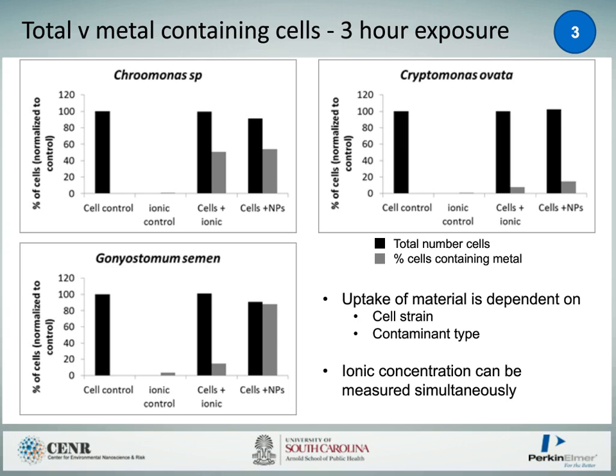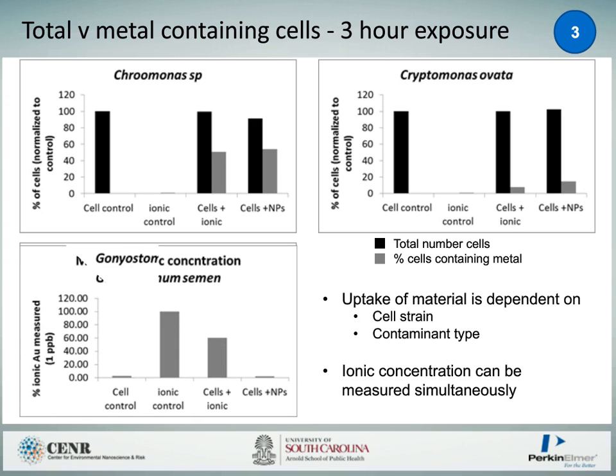You can also measure the ionic concentration simultaneously. So here I just wanted to show you a quick graph to show you why this is important over time. Our cell control had no ionic material in it, nor did our cells plus nanoparticles. Our ionic control had 1 ppb in, which is 100% of the material. Our cells plus ionic after 3 hours reduced, went down to about 60% of our original amount of ionic material. So we lost 40% of our ionic material. This means over time, our exposure is actually changing because of uptake from the cells.